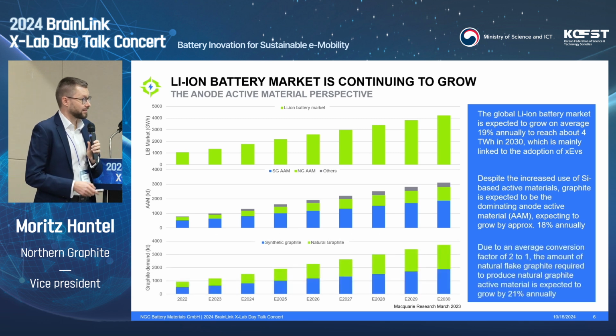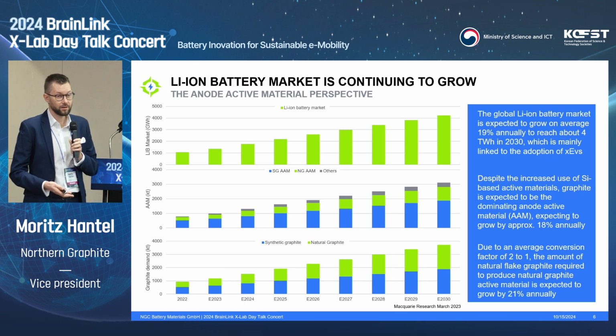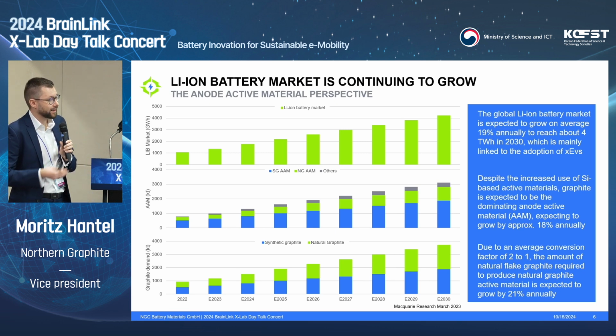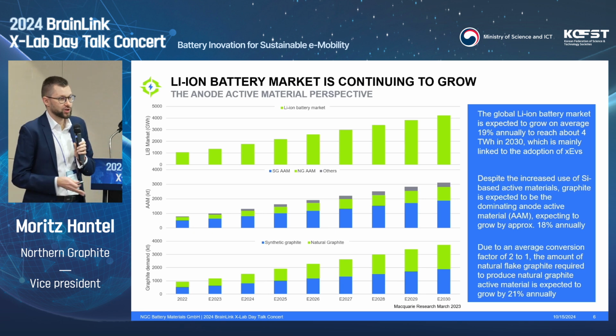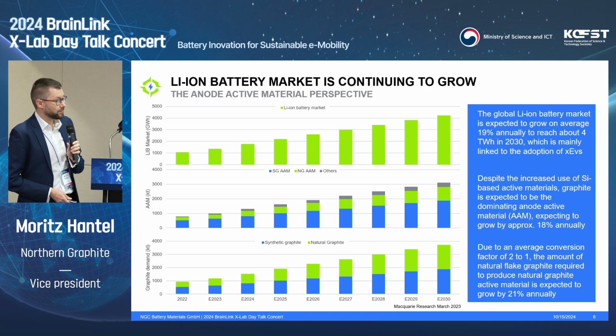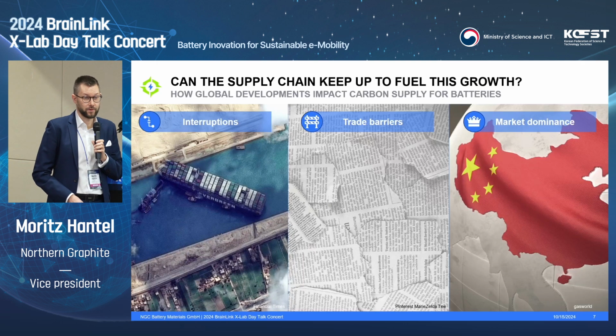Looking now into graphite, which I think is also an interesting topic, we have two kinds of graphite in the market. We have the synthetic graphite, where you produce synthetic graphite directly into an anode active material, with a conversion ratio of 1:1. And then there's the natural graphite, where you mine flake graphite and then process it to anode active material, and in this case the conversion factor is 2:1. Meaning, looking at the demand for graphite, we are talking around 4,000 kilotons of graphite, which needs to be either synthetically produced or mined by the end of the decade. So the question is, can the supply chain keep up with this?